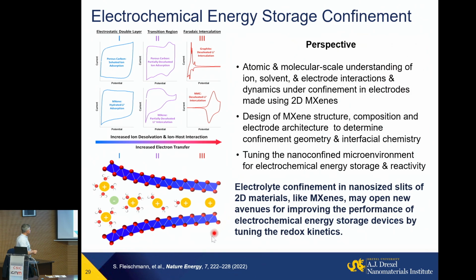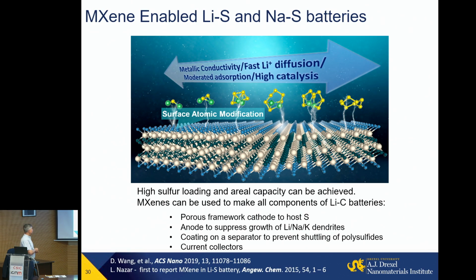And I won't go into further details, but depending on the electrolyte and material, we can go from purely intercalation chemistry like in a battery to double layer storage to intermediate pseudo-capacitive storage. Can use other types of batteries. We can use it in metal sulfur batteries. We work with a company, Giner, on lithium sodium sulfur batteries, where MXenes can catalytically decompose polysulfide. They can prevent transport of polysulfide through materials.